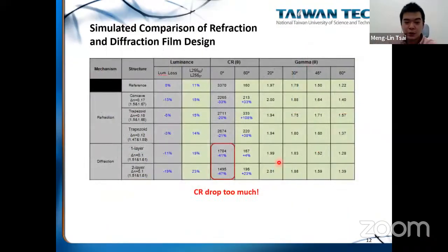So this will cause a difference between the refraction structure and the diffraction structure in the contrast ratio of the display. Normally, without any type of optical film, we have a contrast ratio at 0 degrees of about 3000, but for the large angle direction, it drops to about 160. So what's the reason? The reason is what I mentioned before, the light leakage problem, the large angle light leakage problem.